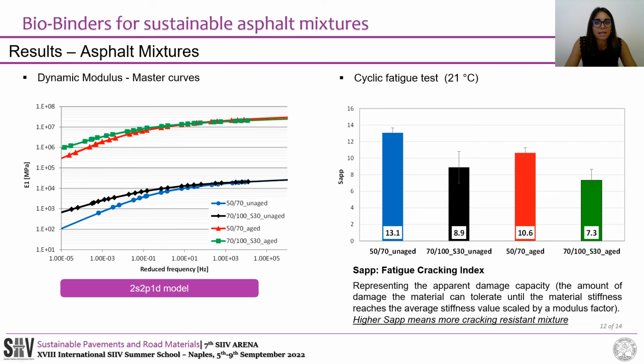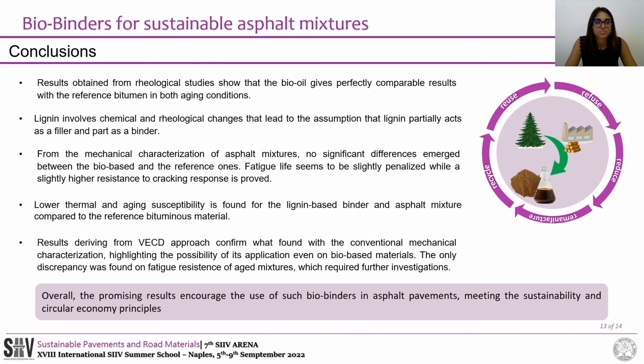obtained by applying the VECD model, while fatigue cracking potential is described by a specific index which confirms a reduction of the lignin-based asphalt mixtures in unaged conditions, even if a slight reduction is also found after aging, and this is the only discrepancy emerged from the comparison between the two mechanical characterizations, so further investigations are required. Given the obtained findings, the following conclusions can be drawn.